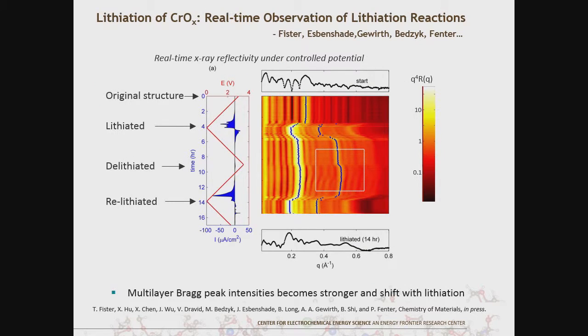So here this is actually a block of X-ray reflectivity data, an in operando study. Each line is an X-ray reflectivity data set, and you can see this yellow thing here is the Bragg peak. This is showing the potential as we lithiate, delithiate, lithiate, delithiate, with the current shown here. You can see that for a while not much is happening until you're down to a relatively low voltage.